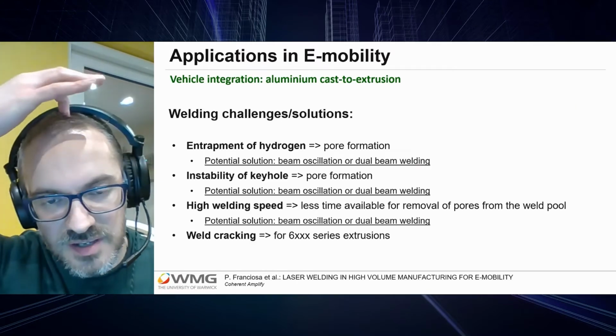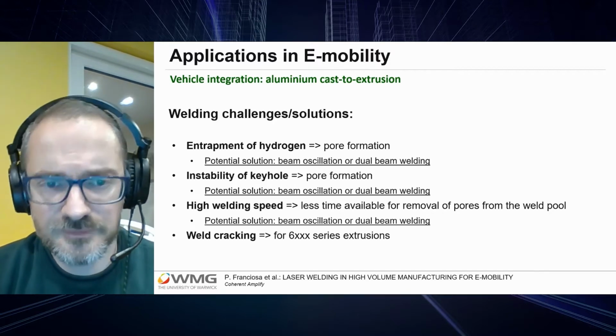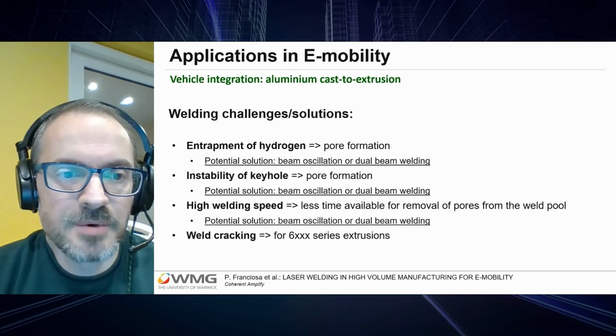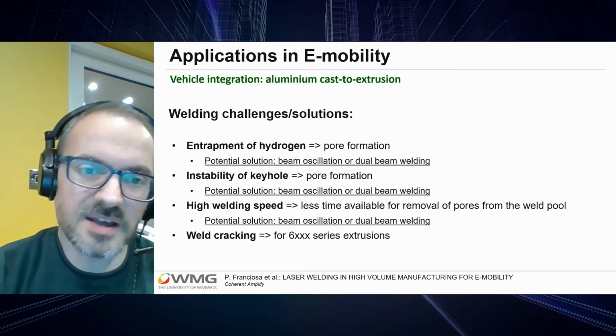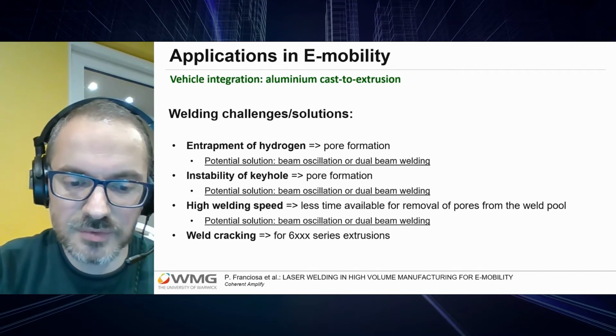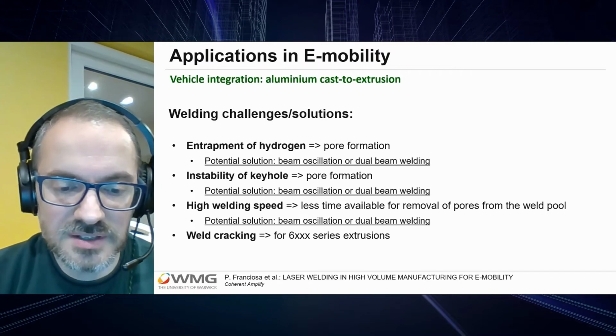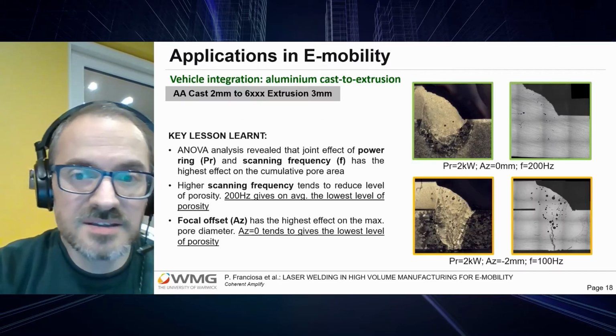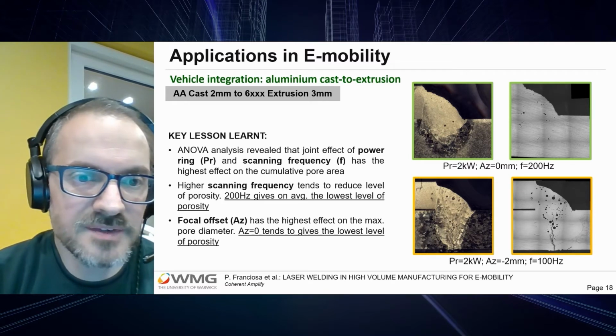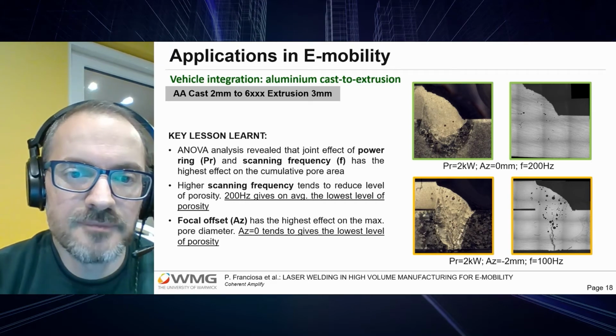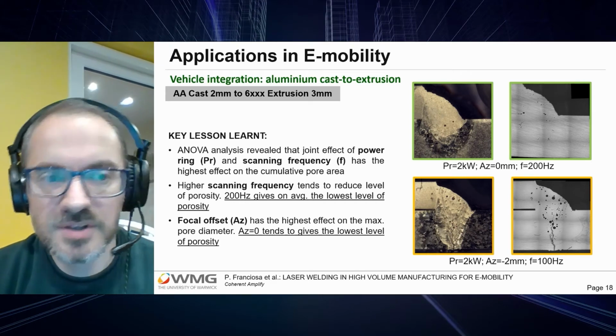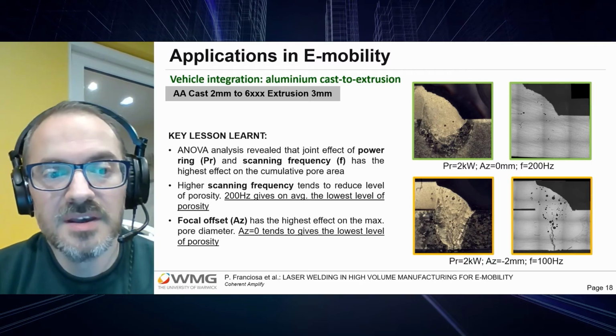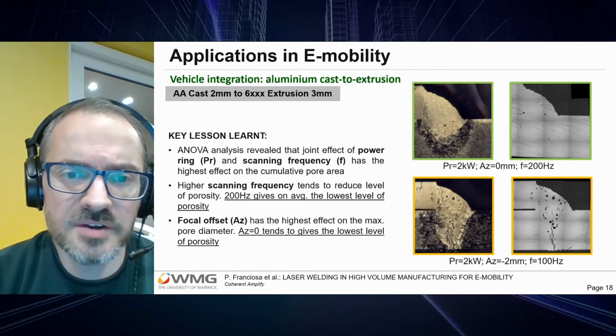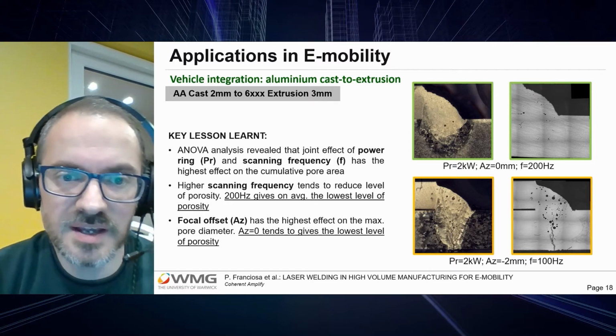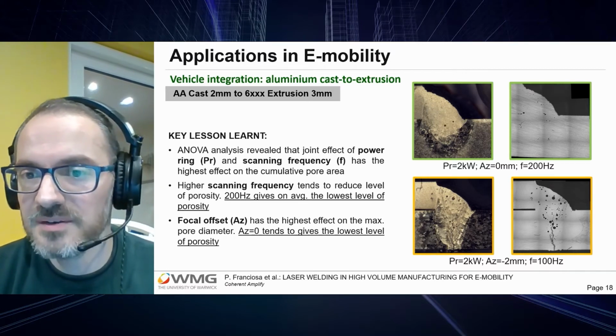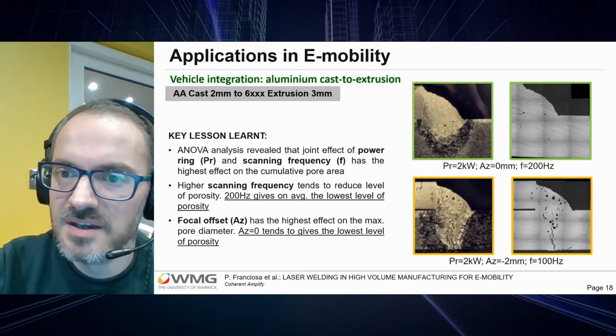The main challenge in this application is mostly the porosity formation, which is a consequence of the entrapment of hydrogen within the base material, within the cast material, during the casting process. So the question is how to get rid of this porosity, of this gas, during the welding process. And this is interesting because after conducting a very comprehensive study with several parameters such as the power on the ring, power on the core, scanning frequency, scanning width, and focal offset, we realized that the joint effect between the power on the ring and the scanning frequency is the predominant effect for the reduction in porosity, as you can see now from the cross sections.